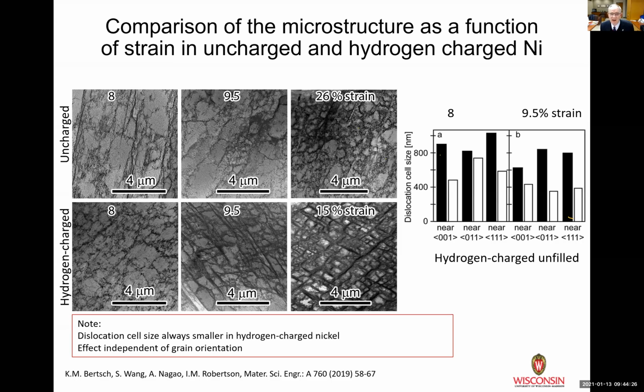If you look at 9.5 uncharged, you'll see, yeah, you're starting to see a cell structure in patches, but it's not uniform. 9.5 in the presence of hydrogen, it's pretty uniform. And certainly, if you look at 15% strain, if you were just to put these samples down in front of anyone, my guess most people would say that the one I've labeled 15% strain actually had the 26% strain because it looks more evolved. It is more evolved, but it's got hydrogen there. But this is the kind of information you can get today.